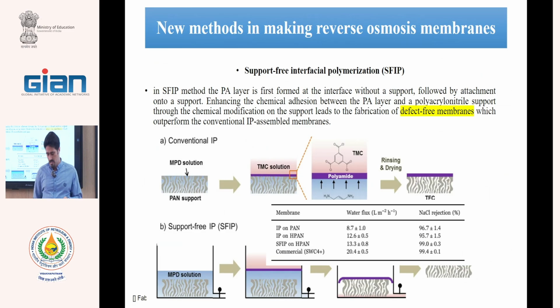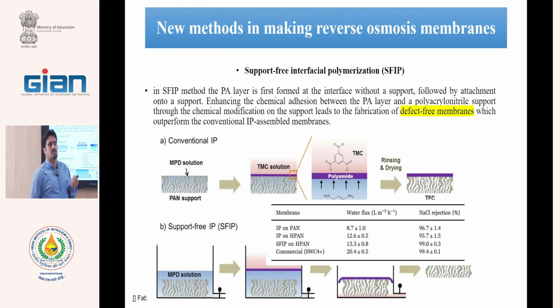Support-free interfacial polymerization. The most effective parameter in the fabrication of RO membrane is the support properties. If we have a suitable standard support, we easily reach high rejection. But when we have a bad support, the rejection is not good. Most students have a problem in the fabrication of a good support. As I said, the control of phase inversion conditions is very hard. Therefore, some days we have a good membrane, and on other days a bad phase inversion membrane, and this support influences the RO membrane. Therefore, it is suggested that we prepare support-free interfacial polymerization.